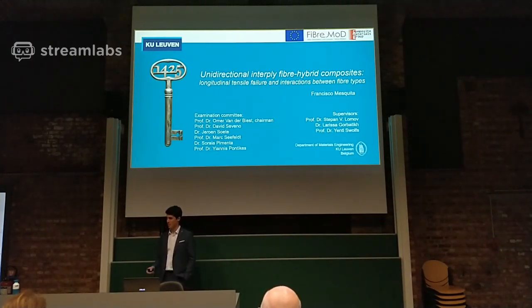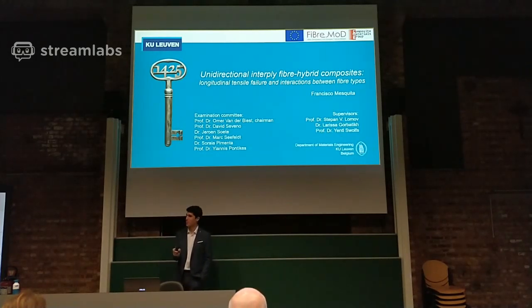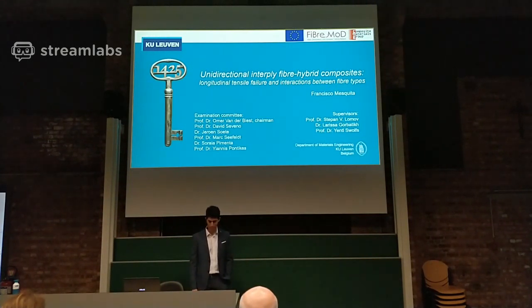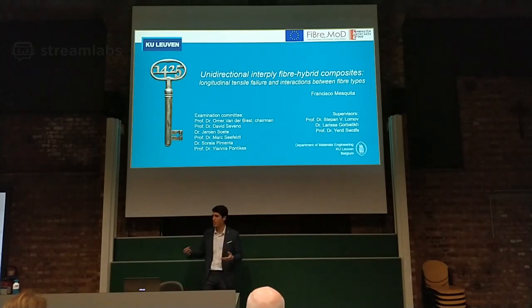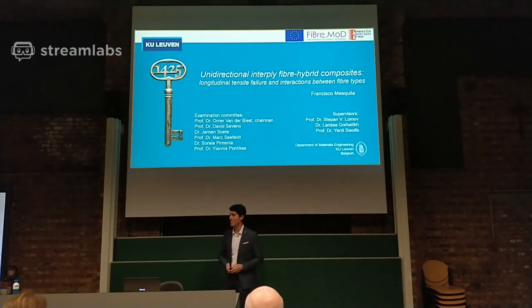So you mean improvements in the method of the tomography itself? Yes. In your experience, what would be the biggest improvement that is needed to achieve? Well, for sure, for example, the delamination propagates in a quite fast manner. So in order to be able to get several data points of the propagation of the delamination, we need to get these scans quite fast. And by fast, we did here in my thesis 9 seconds, but I think we would need to do it even under 1 second.